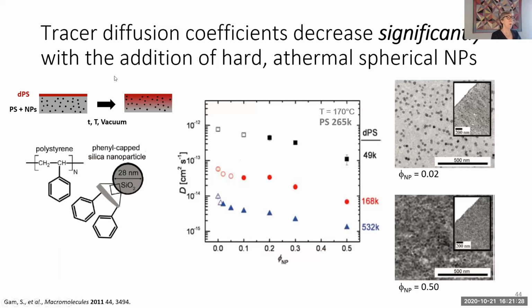So it's the same sort of experiment, deuterated polymer on top of the nanocomposite. We measure the concentration profile and extract a diffusion coefficient. So from the TEM, you can see that we have nice, well-dispersed nanoparticles even to high concentrations. And as we add nanoparticles, the diffusion coefficient decreases. So again, not like the confinement, the diffusion coefficient decreases quite substantially and for a range of molecular weights. So to put this all together, we have a particle size, we have a concentration of particles, and we have a polymer molecular weight.